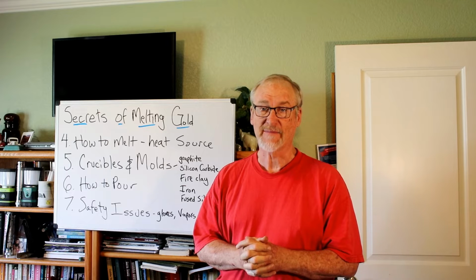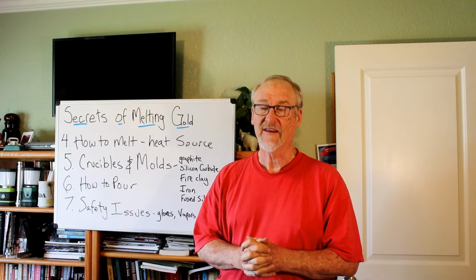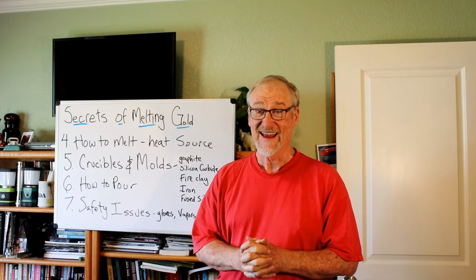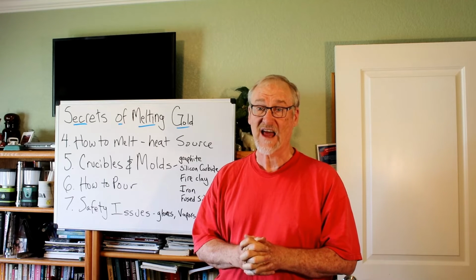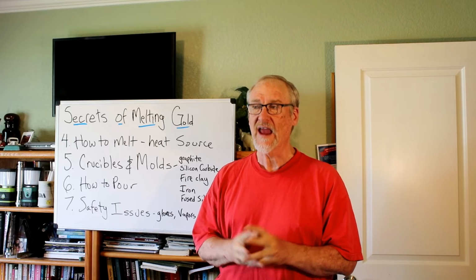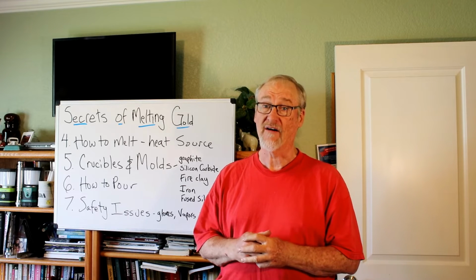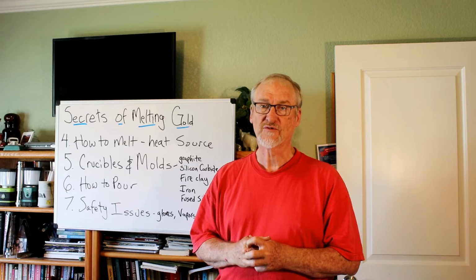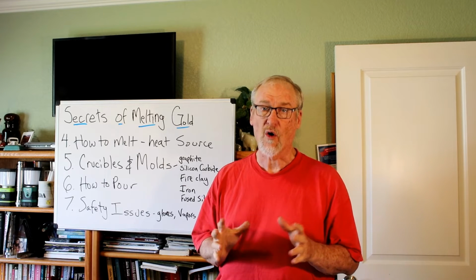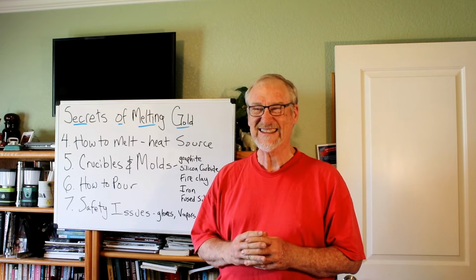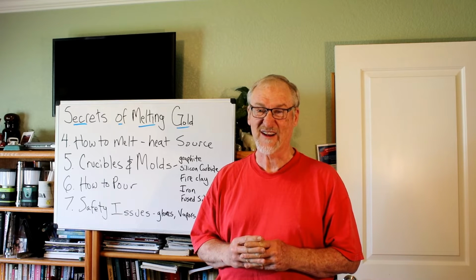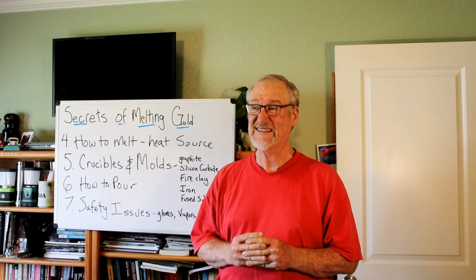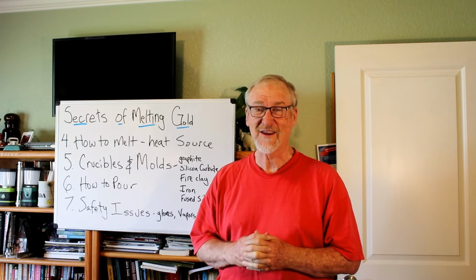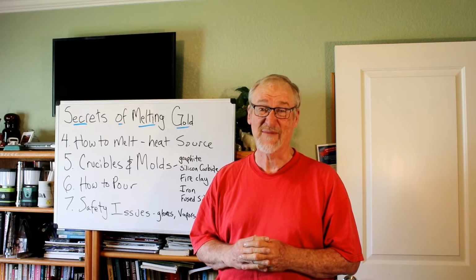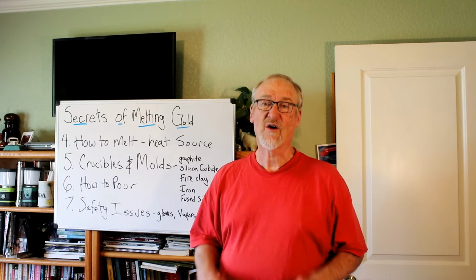The upper limit of that is about 1150 centigrade, and the melting point of gold, like I say, is 1064. So it's less than 100 degrees above the melting point, and you want to get to a good amount above the melting point. So it almost requires that you go over the recommended limit. And it's not good for the durability of the furnace. So although I know they sell these things and they say, yes, it will melt gold, the one time I tried to use one, I had a hard time melting silver, and silver melts at almost 100 degrees lower than gold does. So I don't recommend these things.